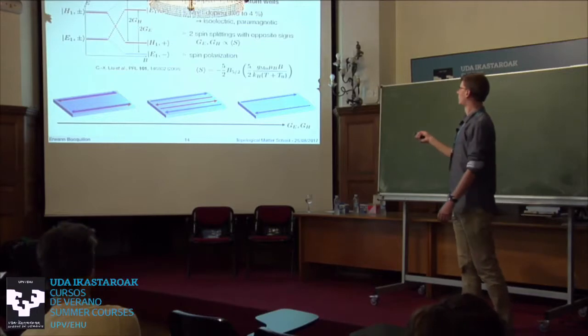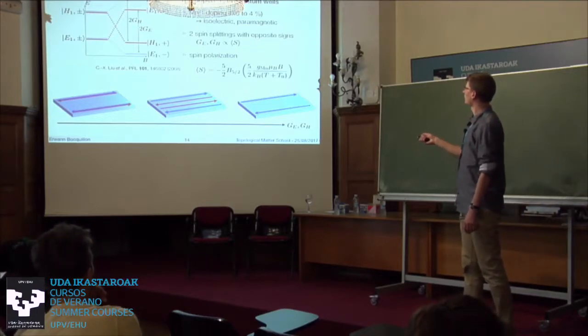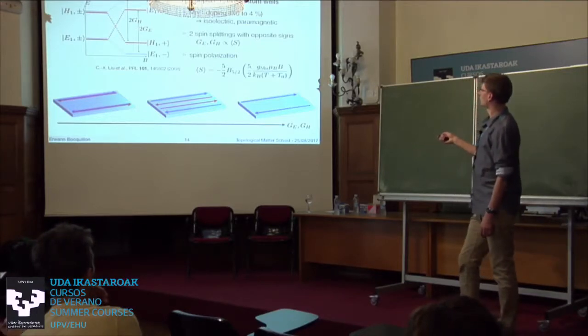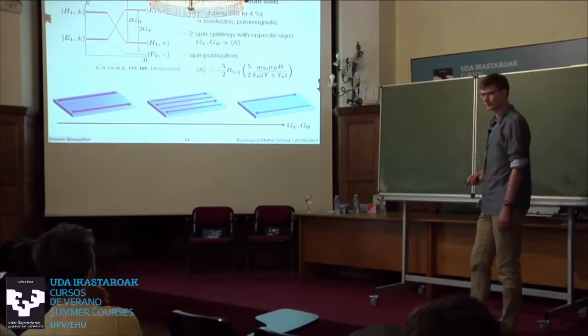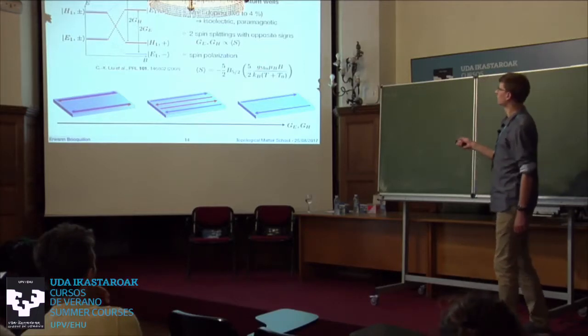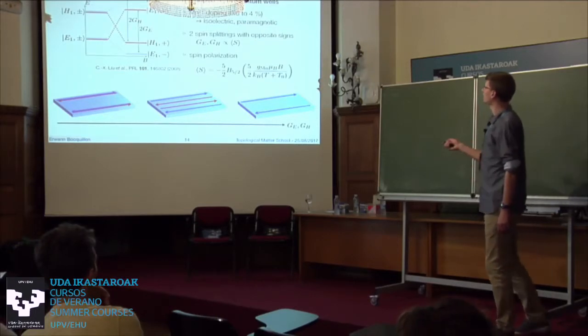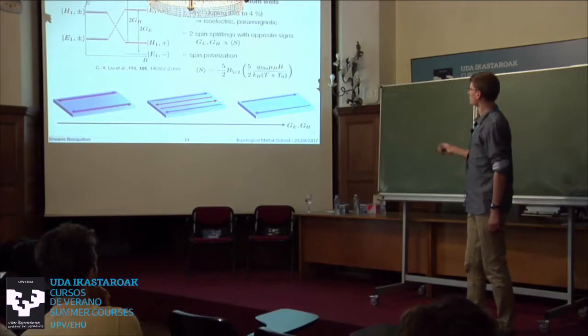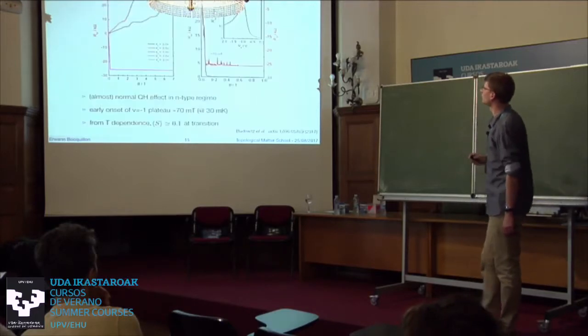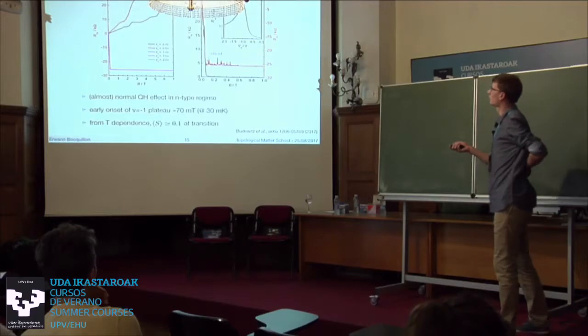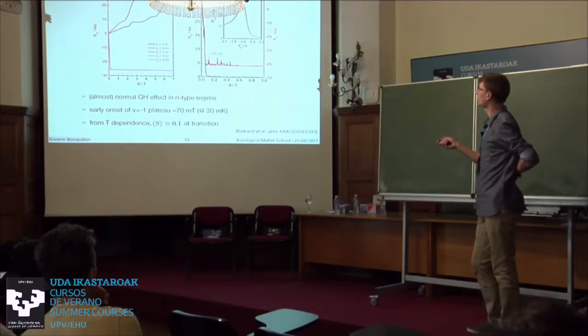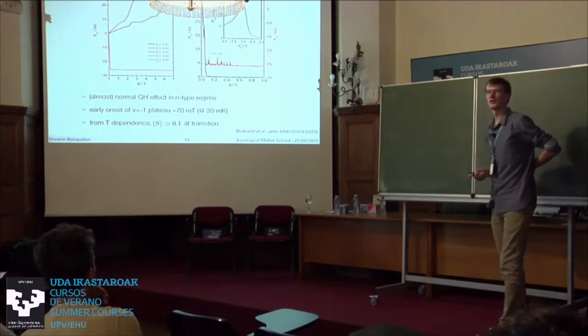And there's a formula for the spin polarization which comes from standard paramagnetism. Here, these manganese atoms have 5/2 spins, and this is very dependent on temperature and magnetic field, but if you do that, then you can reach a quantum Hall plateau at very, very low magnetic field. So here you see we have nu equals -1 for a very, very low magnetic field, of the order of 70 milliteslas.